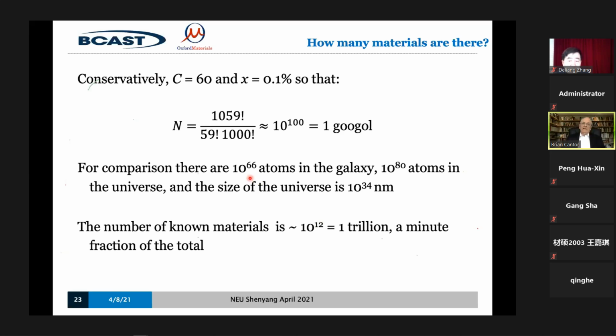So knowing the answer, now we need to work out what the actual number is. How many components can we have? Well, there are 120 different elements, so really we could probably use 120. But of course, many of those are toxic or radioactive or only last for a millisecond or less. So the real usable number is more like 80 or 90. We could say C was 80, and that would be very reasonable. But let's be really conservative and stick to the main metals and the main semi-metals. Let's leave out fluorine and iodine, even though fluorides and iodides are important materials, and leave out things like oxygen and sulfur, because they're usually more like impurity materials. But even so, we've still got 60 elements we can mix together.